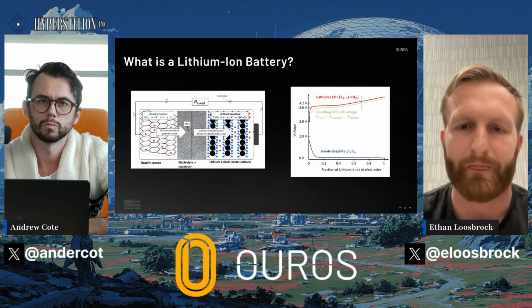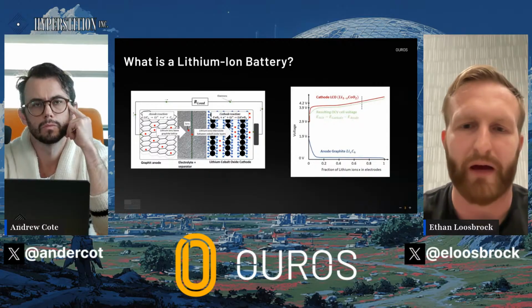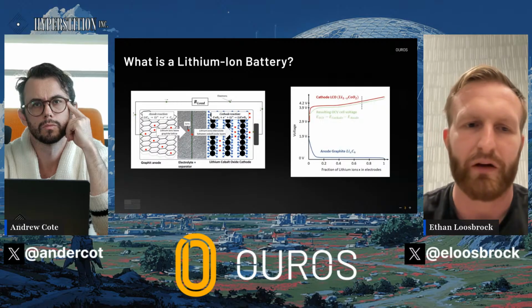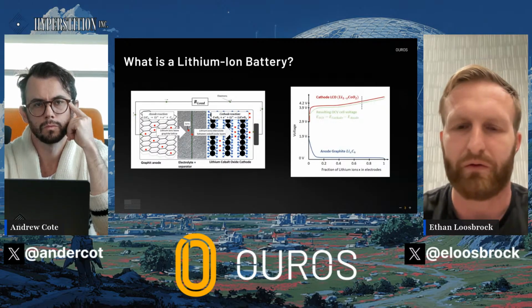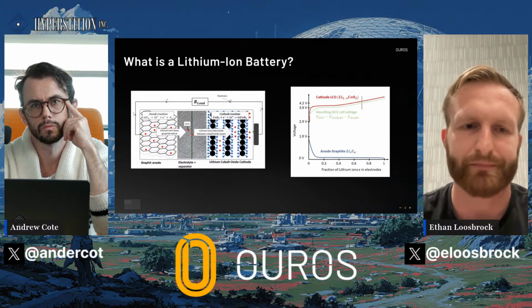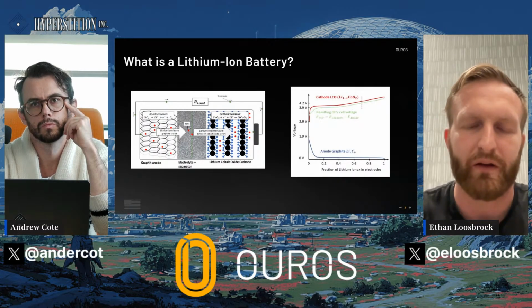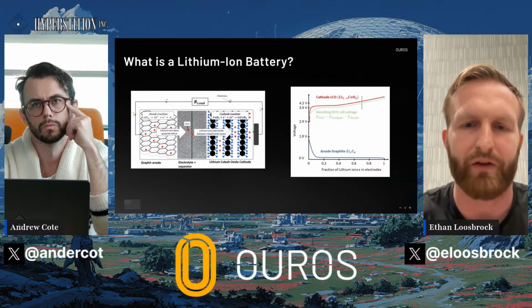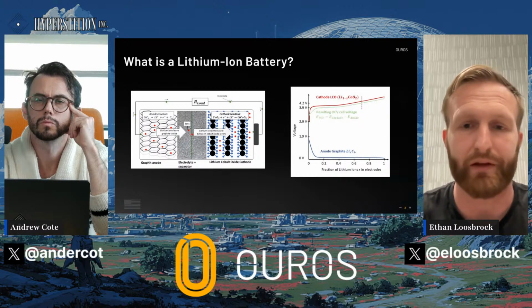In the first cycle when you make a battery, we call that formation, and this typically happens before any consumer even sees the battery. But this step is very important for ensuring the stability of the battery. You do a very slow charge and discharge, and those additives that you put in, if they're working properly, will make a thin film over the surface of the electrodes, and they will passivate the electrodes so that there's no continued reaction, or as little continued reaction with the electrolyte as possible.